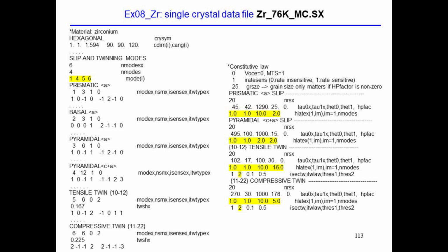So coming to the twinning systems, here you can see that these numbers have a meaning. The secondary twinning, which has a 1, means yes, 0 means no. So 1 means that yes, we are going to allow for secondary twinning, that in the twin we are going to allow for creating another twin. This 2 refers to the twin law. This is the Monte Carlo, the 2 that I was talking about. So this is 1 for the predominant twin orientation, 2 for Monte Carlo, and 3 for the volume fraction transfer